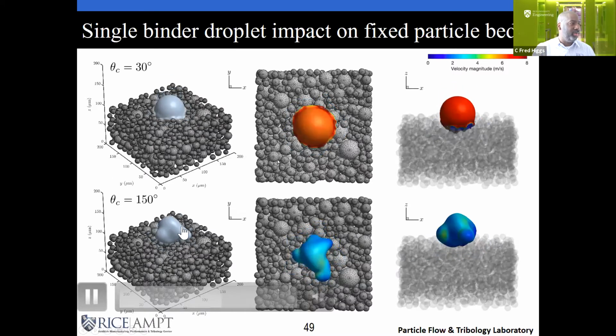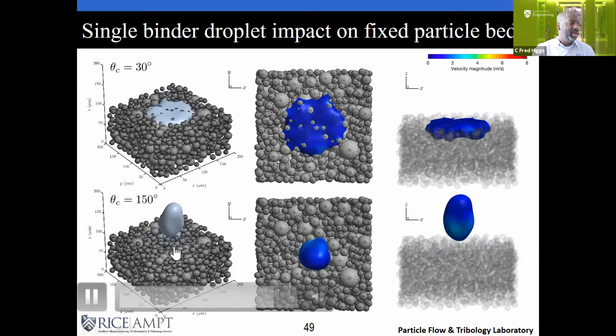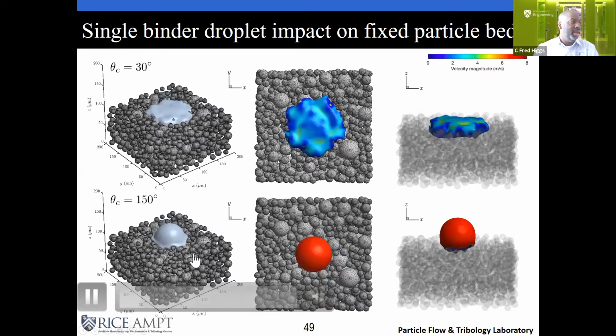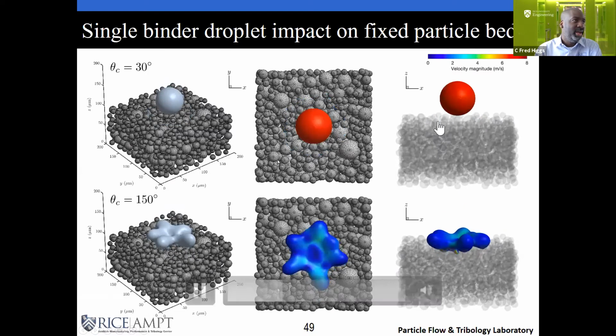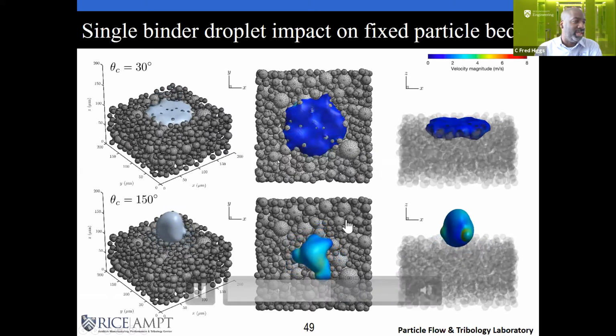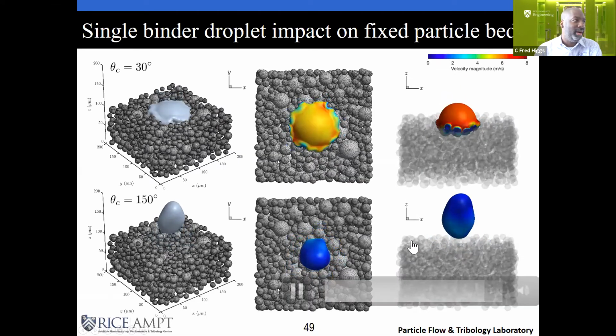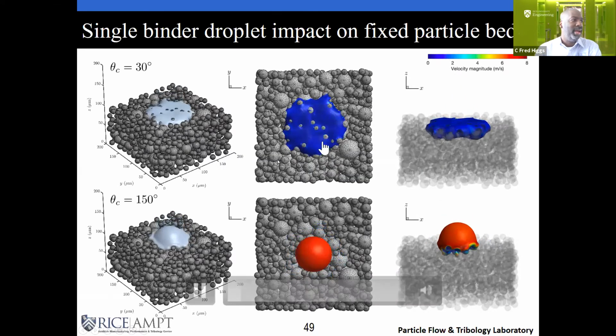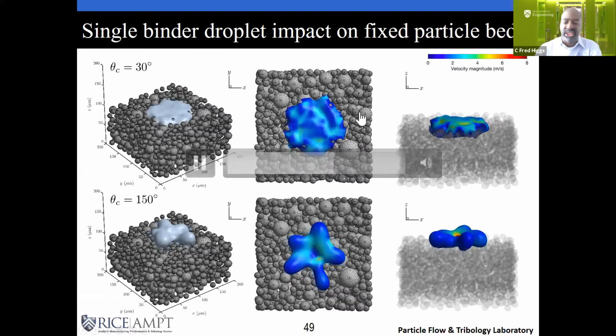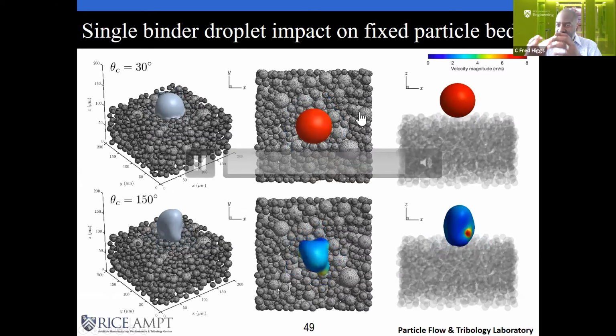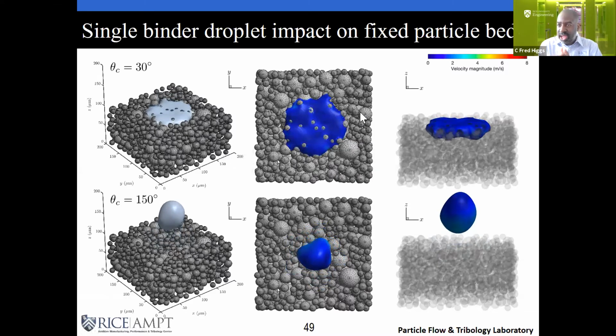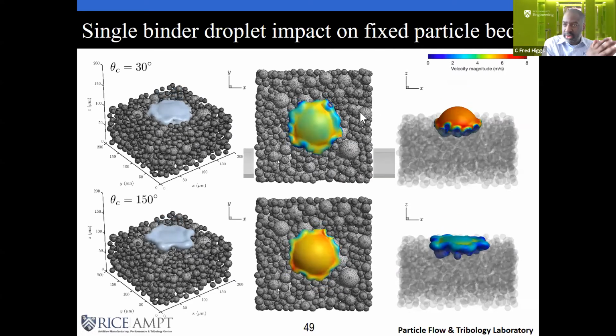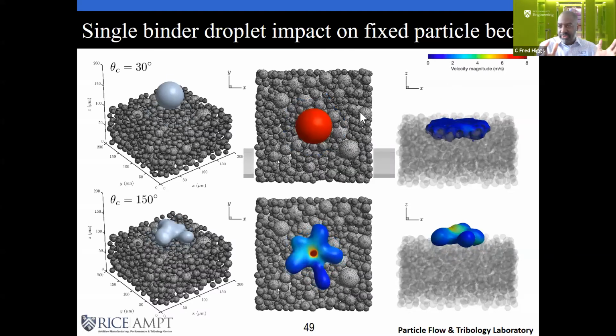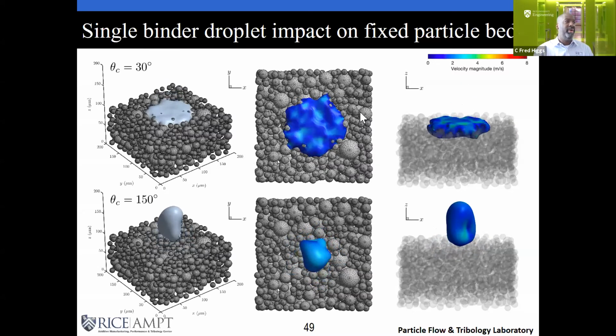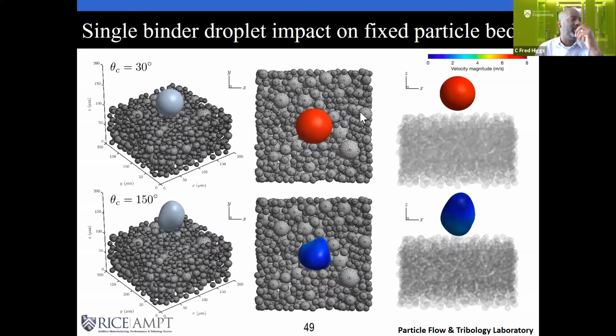This one here is a little bit more hydrophobic, so it comes back up. It's running away from these particles because of the high contact angle there. And here you look at the same simulation just from the top, and this is from a pure side view. And you can see now, this powder bed is fixed for this simulation. We just wanted to look at the fluid behavior against a solid powder film, although the powders are not free to move in this simulation. And so we kind of liked what we saw there.